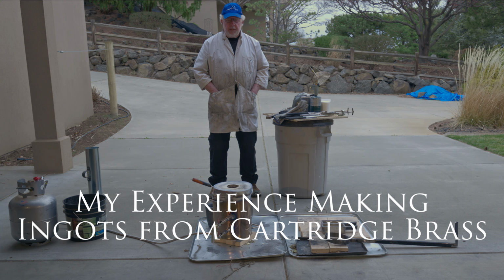This is a lifting tong for the crucible where it grips it on both sides and you can safely lift it up. This is another way of doing that once it's out of the furnace, but I don't like these. They're not very robust. Yes, they do allow you to hold the crucible, but it's kind of tough. Now over here, none of this is hot, by the way. I made a ring out of steel, welded it to a bar, and you can lift the crucible and pour nicely, and that felt a lot more robust to me.